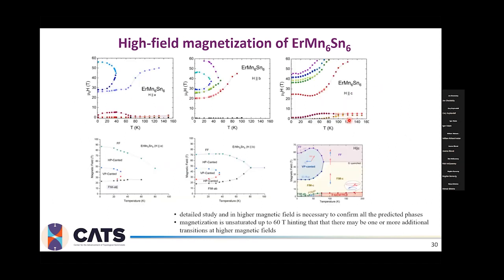And I would like to show all of this magnetic phase diagram, which we were able to observe experimentally, shown on top, and the theoretical prediction, which is at the bottom. The first thing we can see is that there are more transitions predicted at even higher magnetic field, which we were not able to see. And as I mentioned earlier, the magnetization stays unsaturated, which may suggest that there might be more metamagnetic transitions showing up at higher field.